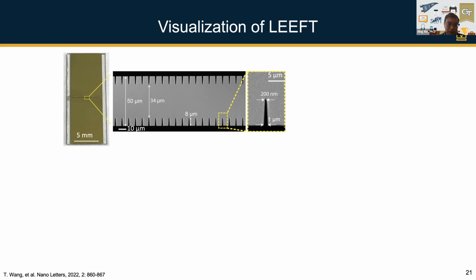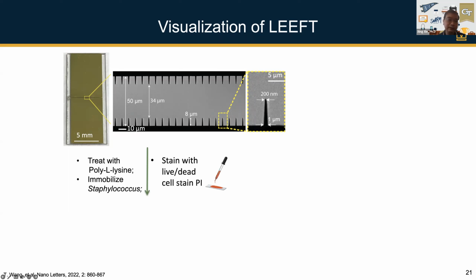But even if we fabricate them and they are durable, it's very difficult, almost impossible, to see them under a microscope. Also, instead of using nanowells, we have the bottom part a little bit thicker, because if you have these very thin, uniform diameter nanowells, they would be very easy to peel off from the system. Anyway, we end up with this design with these nano wedge structures,